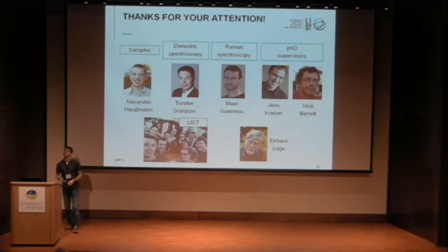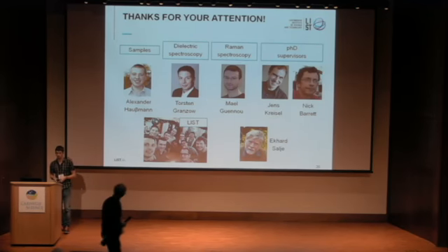I know there are some experiments where they look at domain wall motion. I do not think they really find a law linked to this, and if they are able to know if it is due to defects or not. But lithium niobate is one of the samples where you have strong evidence of pinning of domain walls at the surface and really bowing of the domain wall on defects. So there is obviously a link between both, and some pinning.